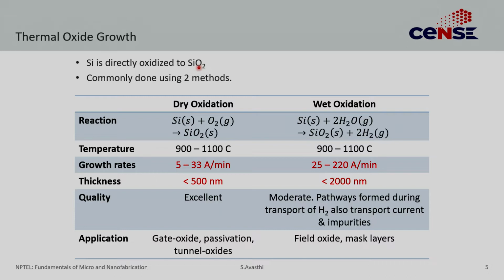The dry oxidation uses oxygen gas. Now, this is the simplest thing you can arguably do, right? You can just expose silicon to pure oxygen, form silicon dioxide. The reaction is fairly simple. You need temperatures of around 900 to 1100 degrees C to do this at a rate that is useful. Around 800 oxidation starts at very low growth rates. At 900 it becomes reasonable enough.